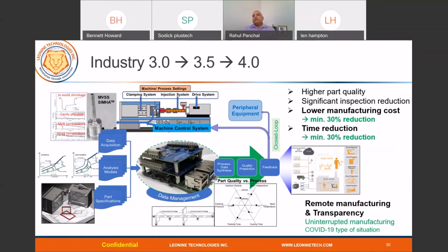If you cannot provide accurate quality prediction, you still have to rely on regression models or a lot of statistics, like some of these in-mold sensing technology providers do. They collect the cavity pressure information, measure the part, create these regression models, and then feed them into their system. But it's important to have any technology that provides those predictions directly. By doing that, you can save at least 30% in time and cost related to inspection. That inspection reduction will reduce your manufacturing cost by at least 30%.